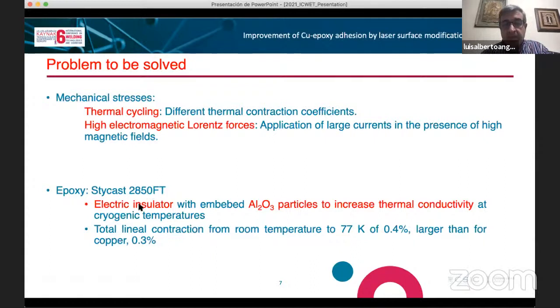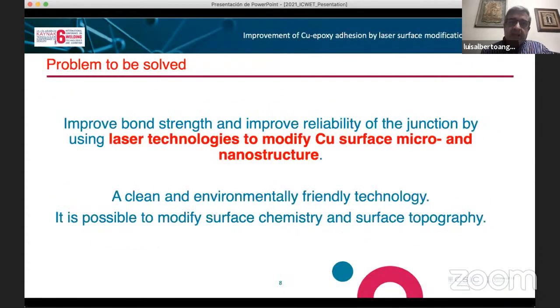Because it is an electric insulator, but we have alumina particles that increase the thermal conductivity of this epoxy, mainly at cryogenic temperatures. And also, this epoxy has a total linear contraction from room temperature to 77 Kelvin of 0.4%, that is slightly larger than for copper. So the idea is to improve the bond strength and the reliability of the junction by using laser technologies to modify the copper surface micro and nanostructure.